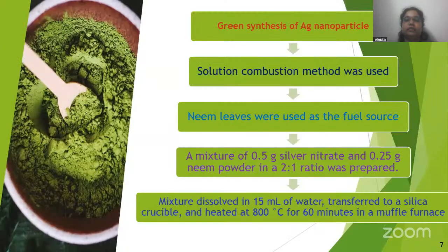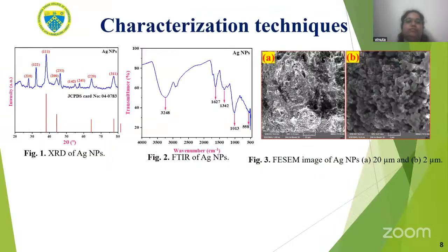Next is the green synthesis of silver nanoparticles. Synthesis of silver nanoparticles was done by the solution combustion method. Here we have used dried neem leaves as a fuel. A mixture of silver nitrate and neem powder in the ratio of 2:1 was used. This mixture was dissolved in 15 ml of double distilled water. We transfer this into a silica crucible, and heat at about 800 degrees centigrade for 60 minutes in a muffle furnace.